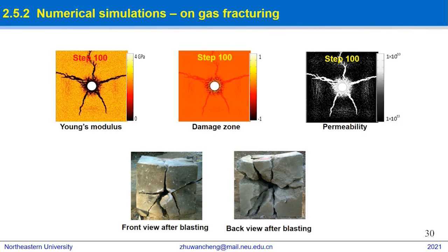Thus, it is reasonable to conclude that the proposed model is effective in capturing the damage process and crack evolution during high-pressure air blasting. The permeability distribution is shown in Figure 3, where white indicates the damaged element with high permeability. It is seen that the permeability at the damage zone, no matter tensile damage or shear damage, increases dramatically.